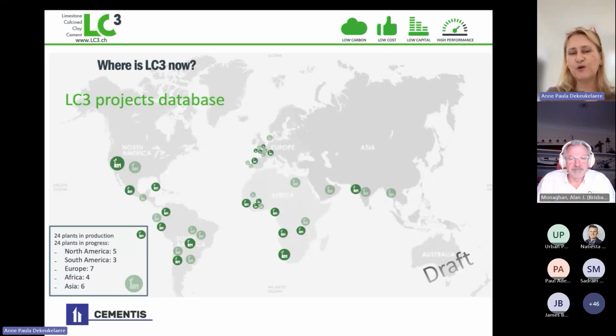Where are we? So the projects are popping up very quickly worldwide. And as Paul said, it's coming on the global south. Because it's implemented very quickly, it has an investment cost because of the calciner, or you can either convert your clinker kiln in a calciner kiln, or buy a new kiln, and that's the investment. But it's not a huge investment. The return on investment there is maximum 5 years. Additionally, producing LC3 costs on average 25% less than OPC. So that's why we see a lot of projects emerging.